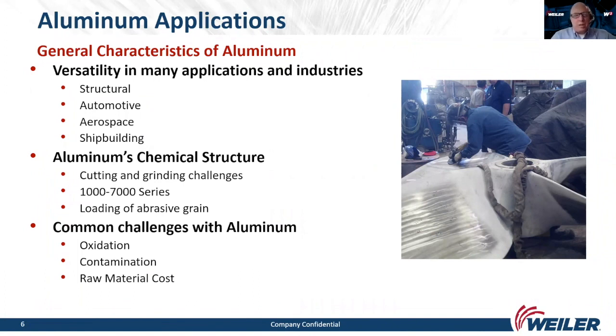Some other common challenges when working on aluminum are, for example, oxidation, which is basically the idea where aluminum is exposed to the atmosphere, it develops an oxide layer. If that oxide layer is not removed before welding the aluminum, it can cause imperfections such as inclusions, which is basically a solid particle in liquid aluminum alloy, or porosity, which can be caused by the gas becoming trapped in the weld pool. It can also result in material burn through. Remove this layer with a dedicated stainless steel brush that's got the finest wire that you can find, stainless steel like I just said, before welding on the aluminum.